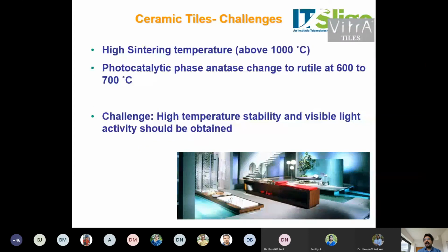We started this work several years back when I was in RRL, Trivandrum, working with Dr. KGK Warrior. Padmanabh sir will know this work. So we started from there, and it has significantly improved since then. There are a number of challenges of using this type of materials. One is that the sintering temperature of these tiles is very high, about 1000 degrees Celsius. And you probably know that when you develop TiO2 in the lab, it is mainly in the rutile and anatase phase. The anatase phase is the photocatalytic phase. And when you heat anatase to a temperature of 600 to 700 degrees Celsius, it changes to a non-photocatalytic phase called rutile.